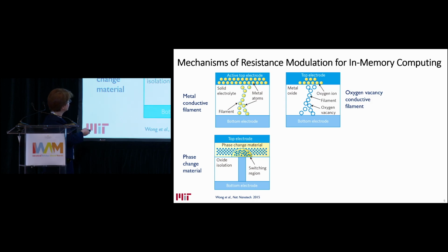The third one that I sketch here is based on phase change of a given compound between insulating and conducting phases induced by Joule heating. And the challenge here has been it's not as low energy and suffers from drift of the programmed state.